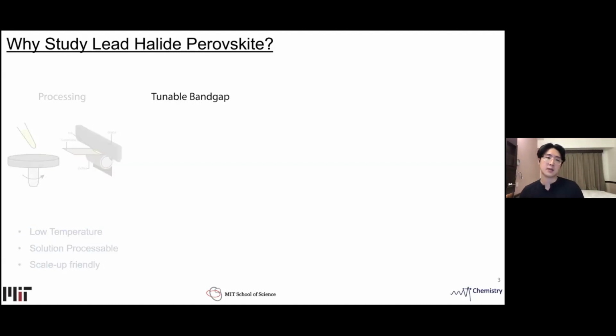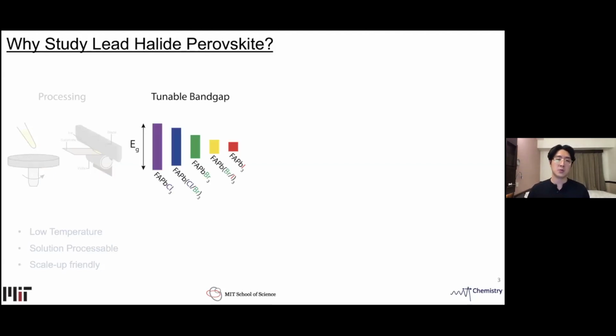Also, perovskites are known to be tunable in bandgap by changing the composition or its stoichiometry. For example, by changing its halide stoichiometry, we can tune its bandgap across the entire visible wavelength range, where a lot of the interesting applications are. These applications range from tandem photovoltaics to LEDs.